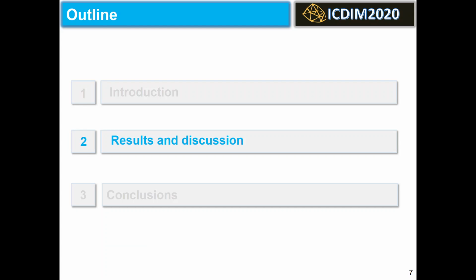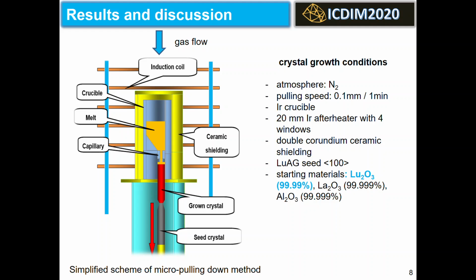Let's move to the results and discussion part. This slide shows a simplified scheme of the micro-pulling down method which I use to grow the single crystals. The conditions are as follows. As an atmosphere, I use nitrogen with the gas flow from the top.